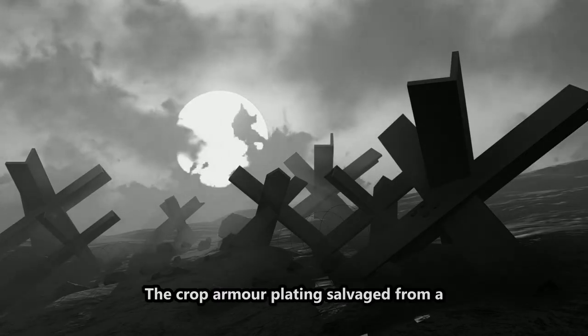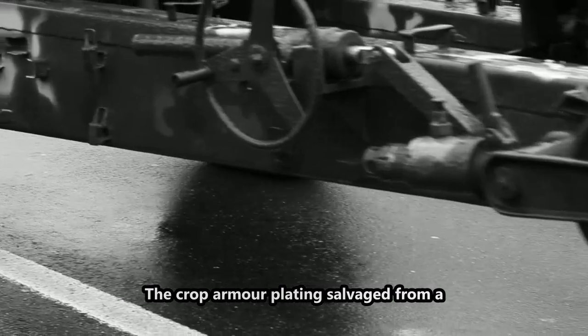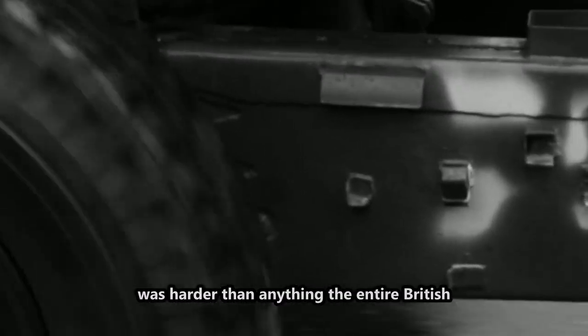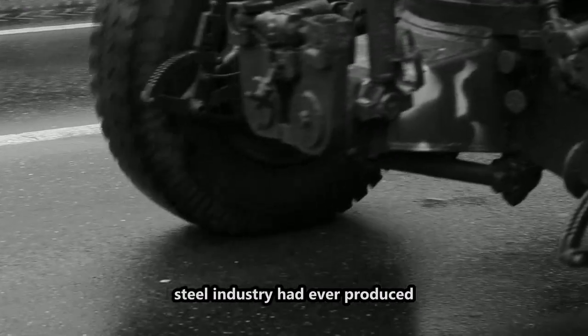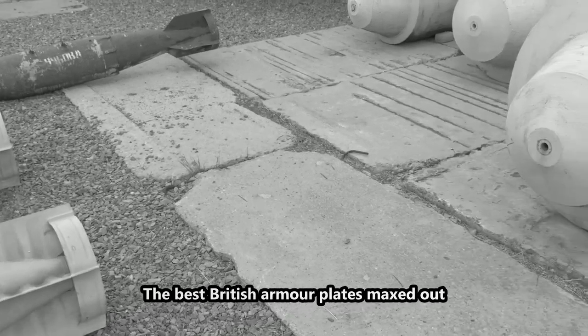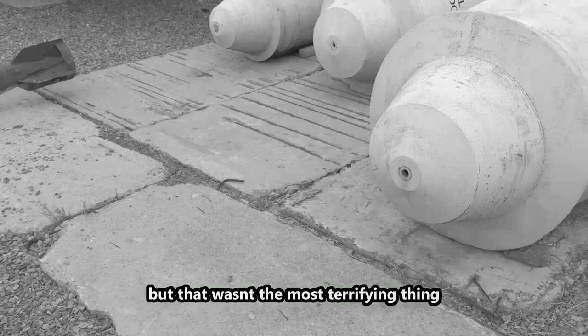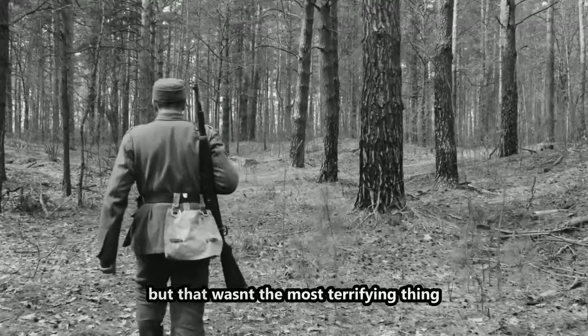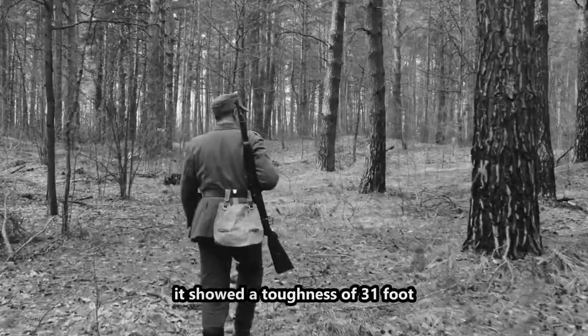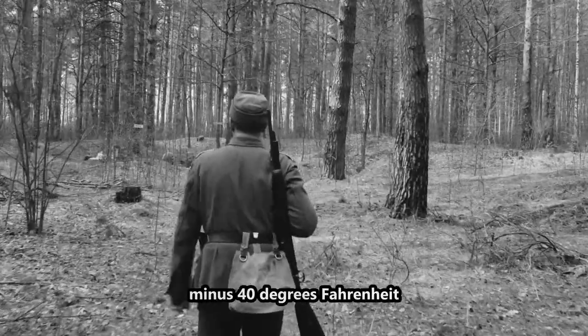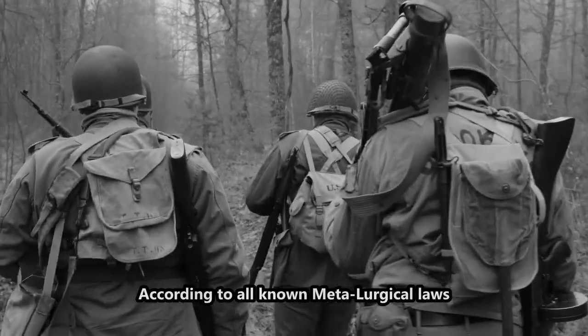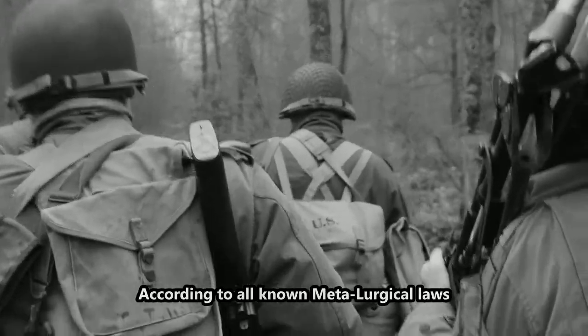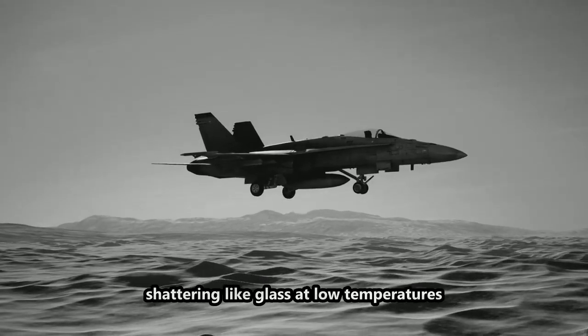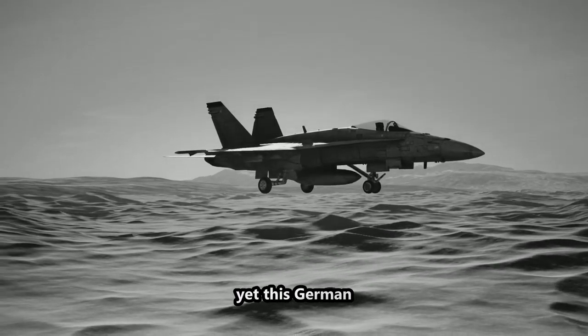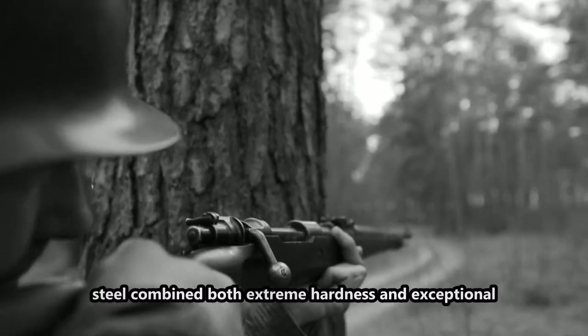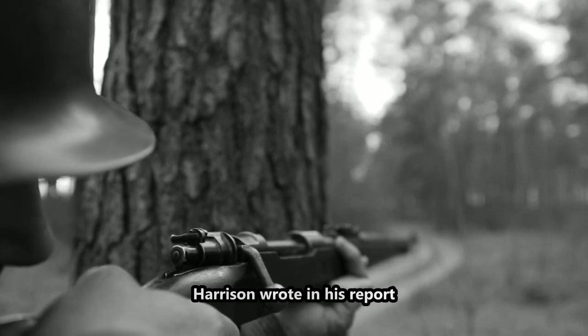The same result. The Krupp armor plating, salvaged from a destroyed Tiger II tank, was harder than anything the entire British steel industry had ever produced. The best British armor plates maxed out at 265 BHN, but that wasn't the most terrifying thing. When Harrison tested the plate for brittleness, it showed a toughness of 31 foot-pounds at -40 degrees Fahrenheit. Impossible. According to all known metallurgical laws, steel this hard should be brittle, shattering like glass at low temperatures. Yet this German steel combined both extreme hardness and exceptional toughness.